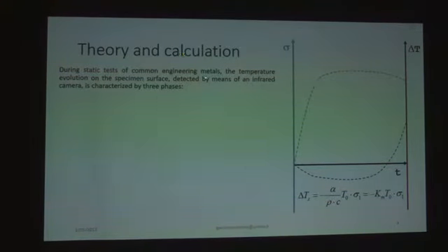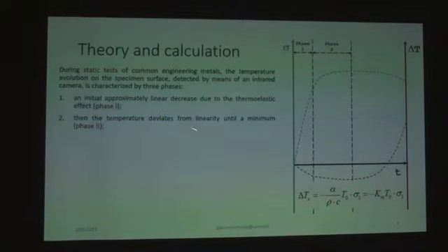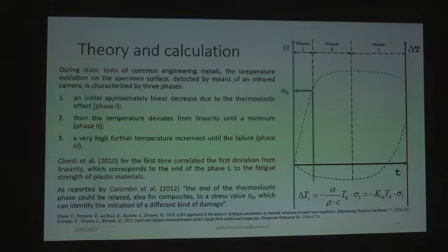During a static test, you can see with the red curve the surface temperature evolution, and you have three stages. The first stage is the thermoelastic equation that you see, a linear decrease of the surface temperature. The second, you have a deviation from the linearity, and after, the third, you have a high increment of the surface temperature until the failure. For the first time, Clienti et al. in 2010 correlate the deviation from the linearity, the end of phase 1, with the fatigue trend of the plastic material.